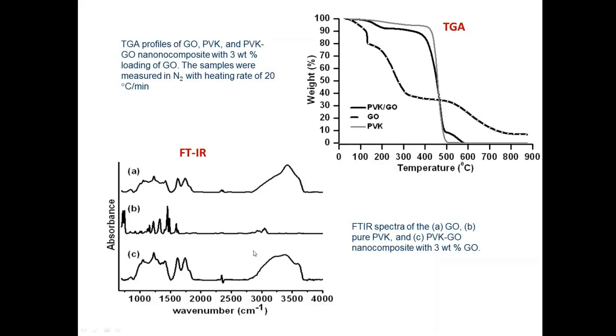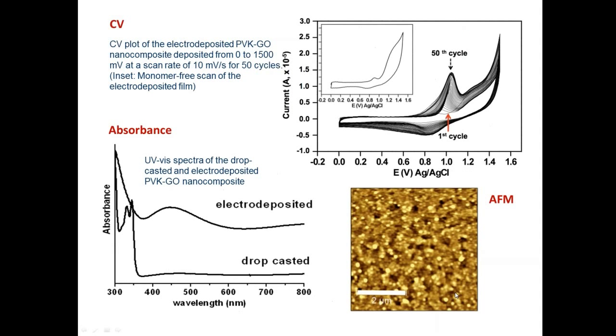FTIR also confirms the form of graphene oxide we have, by the formation or presence of absorption in the 3400 region. Electrochemically, this is relevant because the polyvinyl carbazole actually has an electroactive monomer species in the form of the carbazole. That means the carbazole can cross-link and bring down the graphene oxide to form films, as shown here in the AFM.